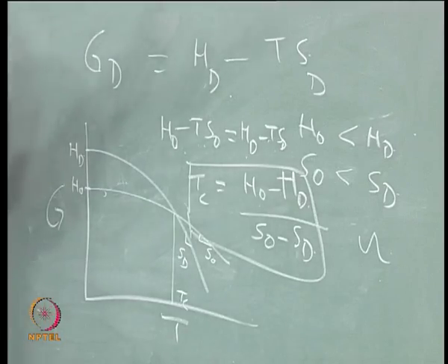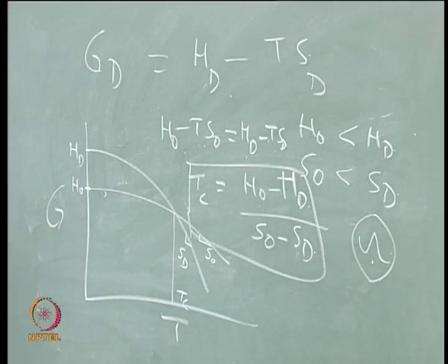If I am taking 50-50, let us say copper zinc, it has a certain value. If I am taking Ni3Al, let us say 75-25, it has a certain value of configurational entropy. It does not depend on whether it is nickel or aluminum or copper or zinc, configurational entropy does not depend on that. So you can see it is this omega which decides it. That is why in certain compounds the transformation occurs at a lower temperature, in certain compounds transformation does not occur until you reach the melting point.